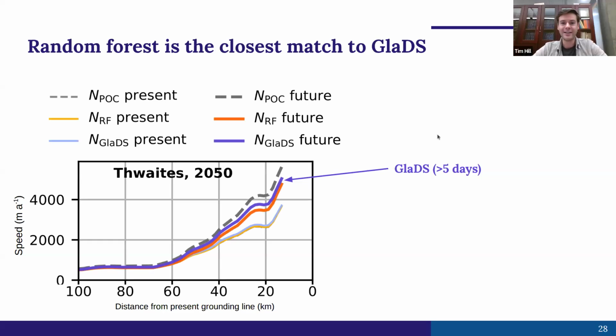In terms of the random forest, GLADS is, of course, our reference. That's the purple curve. But if we use the random forest, we get, for Thwaites, maybe a couple 100 meters per year difference in grounding line speed. But we've taken our computation time from 5 days to run the GLADS model to half a second to predict with the random forest. So to me, that's a pretty good trade-off.